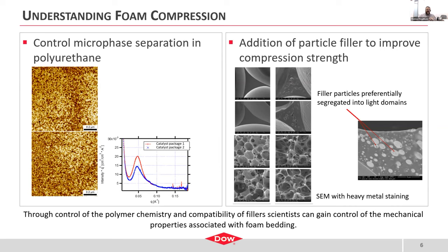So what we often do is make a composite material where we throw polymer particles into the polyurethane formulation such that it acts as a composite reinforcement and gives rise to a harder mattress while maintaining the viscoelasticity of the polyurethane matrix. We can use things like scanning electron microscopy to look at a foam that has no filler particles on the left to a foam that has a number of filler particles on the right. We can also use heavy metal staining in the electron microscope using things like ruthenium tetroxide to really bring out the contrast in those particle-filled systems. We can see these filler particles that are preferentially segregated into these polyol-rich domains within the polyurethane foam, giving rise to the increased mechanical strength or the increased compressive strength of the foam mattress, without sacrificing the viscoelasticity.